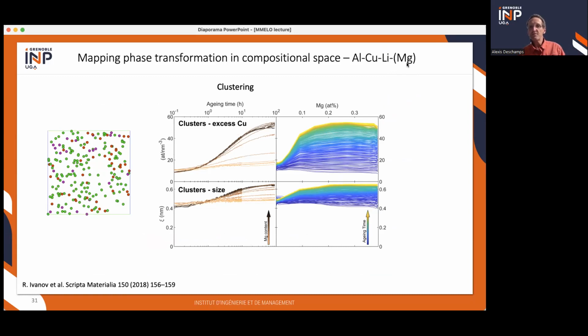So basically, when you look at these systems, you don't see magnesium because it's almost the same atomic number as aluminum. So you just see the clustering of copper. And these are very, very small clusters, like 5 angstroms in radius. So they cannot be characterized by many other means as small angle scattering. And small angle scattering tells you how much of these clusters you have.